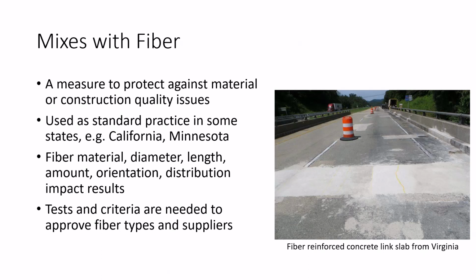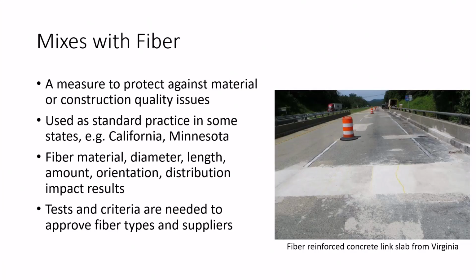In California and Minnesota, this is standard practice, to have fibers in their deck mixes. But one thing that is important to emphasize is that if you just add fibers into your mix and think that it's going to work, that's probably too naive an approach. The types of fibers, the various suppliers, the size of fibers, orientation, and distribution all have a great impact on the results. And of course, just adding fibers also changes the workability of the mix. So just like any innovation, doing some iterations and improving that mix over time is what's needed here.